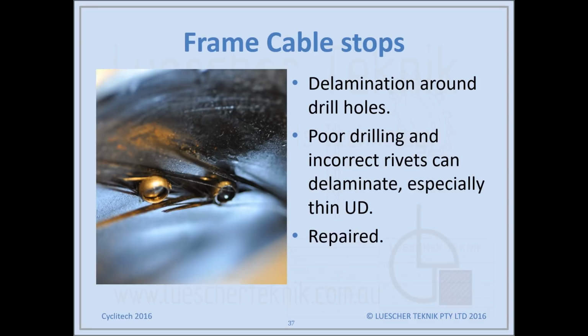On frame cable stops, you often see delamination where the rivets go through, from a combination of poor drilling and poor rivet choice. Now this has improved, so that better rivets are being used. So instead of the shank expanding, the shank just pulls down. And often fabric is used on the internal surface to prevent this sort of splintering of a unidirectional laminate, like has happened in this case. So these can be repaired. We can remove the rivets, do a repair on that, and then reattach the cable stop using correct rivets and adhesive.